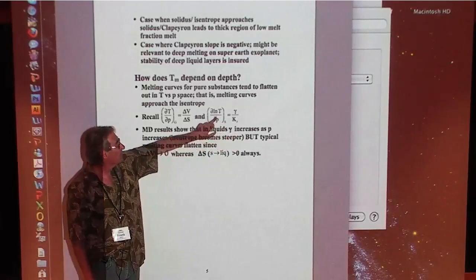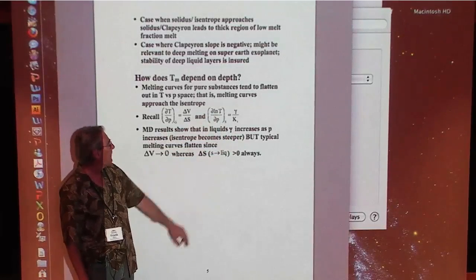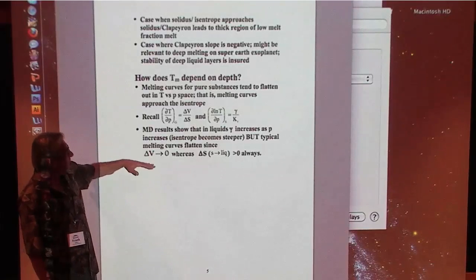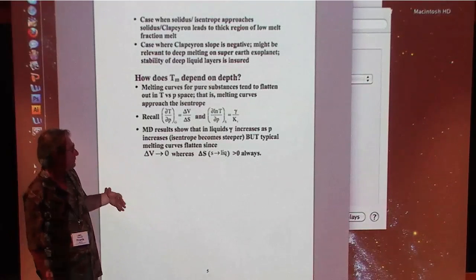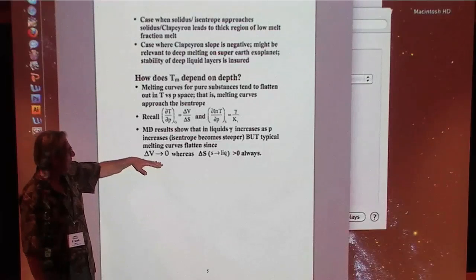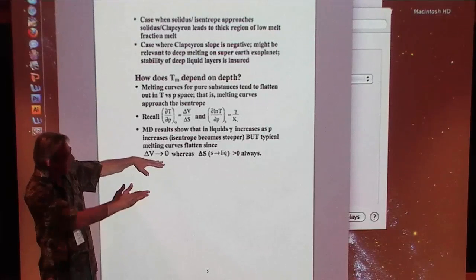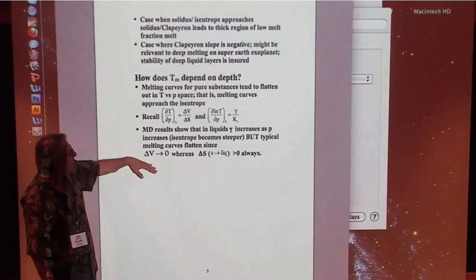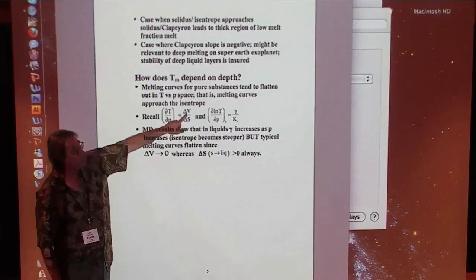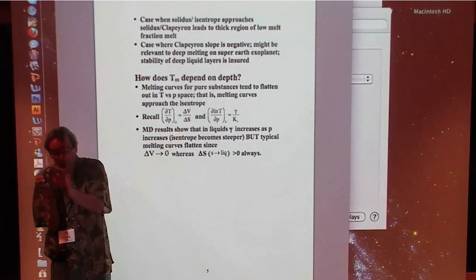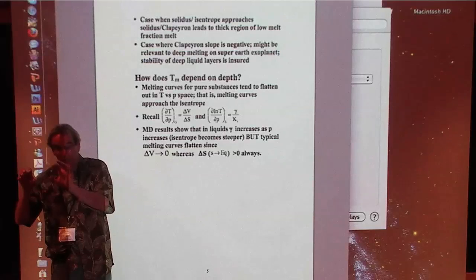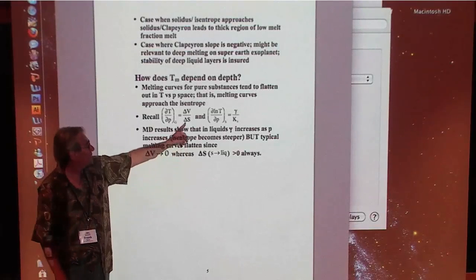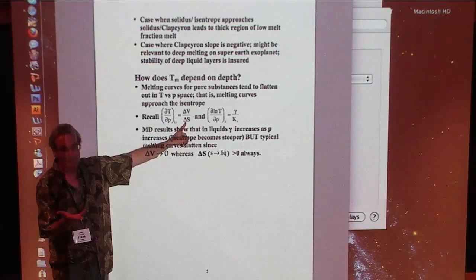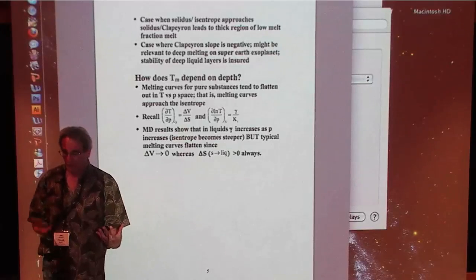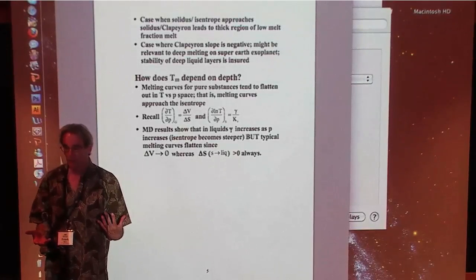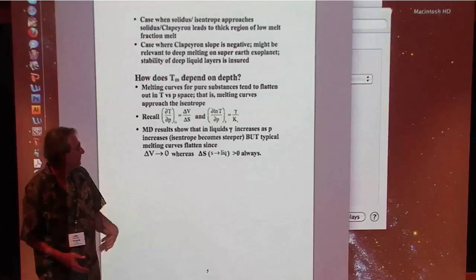Right? So this is getting steeper. But when you look at melting curves, just empirically, going back to Bridgman and people like that, and I'll show you some examples here. Remember that the melting curve slope is basically delta V, the volume change between liquid and solid, and the entropy change. Well, the entropy change is always positive. When you go from a solid to a liquid, there's an increase in entropy, right? You don't have to be that smart to figure that out.